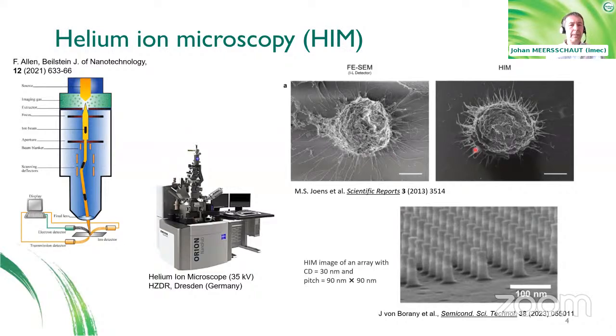So this is why helium ion microscopy sometimes is used for the analysis of organic materials. At the same time, this technique has a very good depth of focus, and therefore it can be applied to look at the morphology or the surface of materials. One property that distinguishes this technique very much from electron microscopy techniques is that it is not very much dependent on the surface charging of the material. So this imaging technique can be used for the imaging of highly insulating materials.